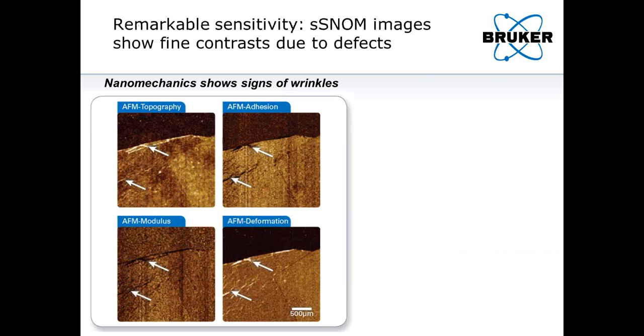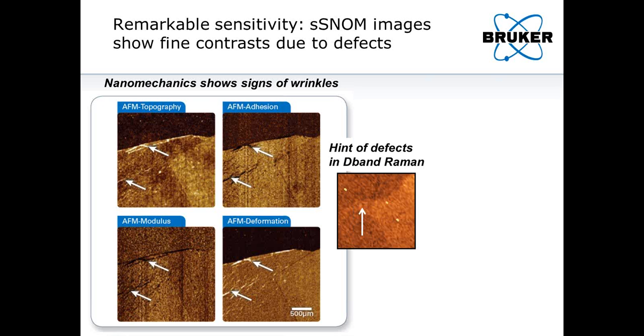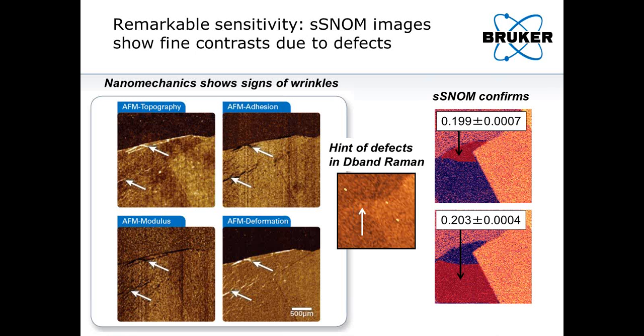I show that on the next slide, and here the combination of nanomechanical measurements allows us to see some hints of wrinkles, which indicates that this portion of the single-layer graphene may not be attached to the surface as well as the rest of it, or perhaps there's some deformation in this surface.